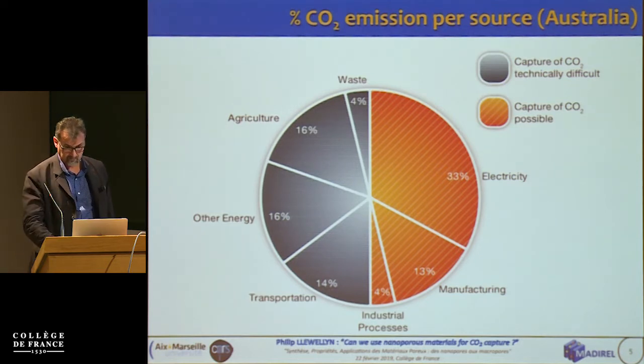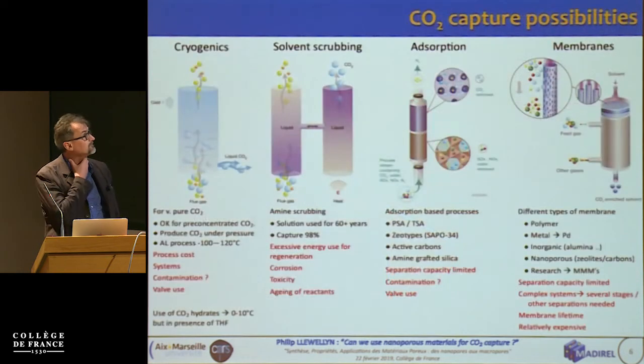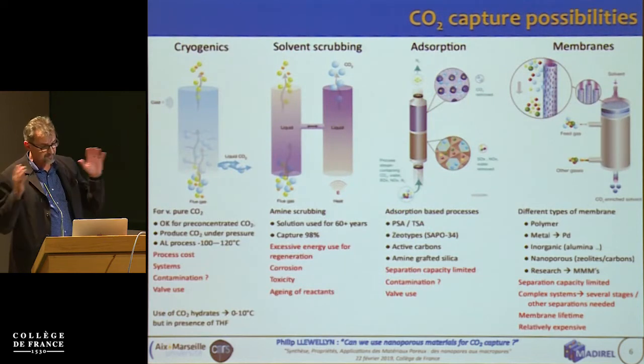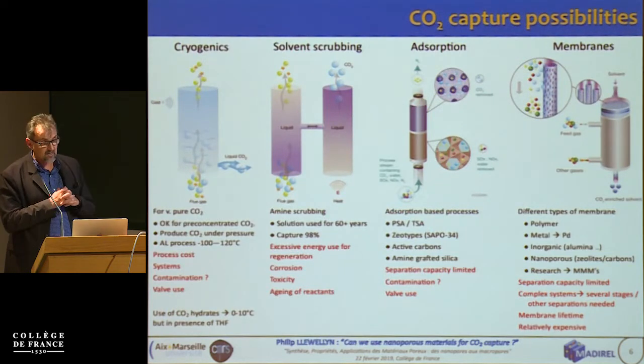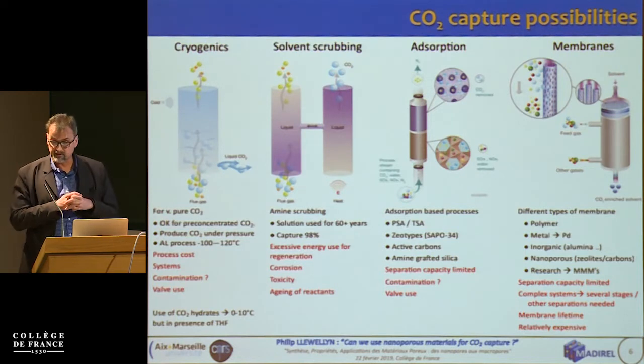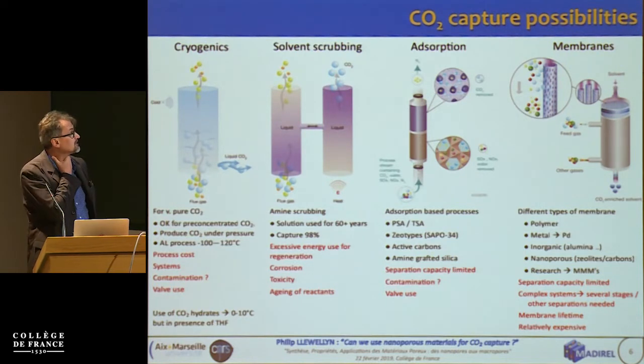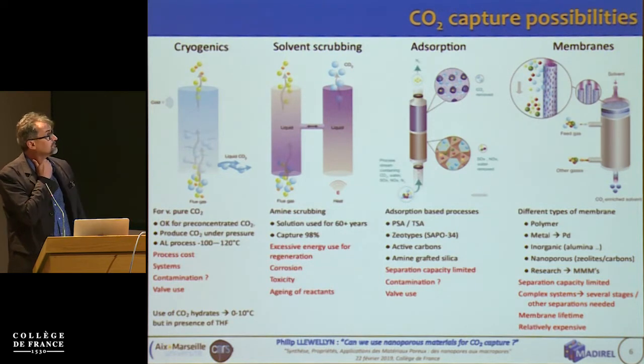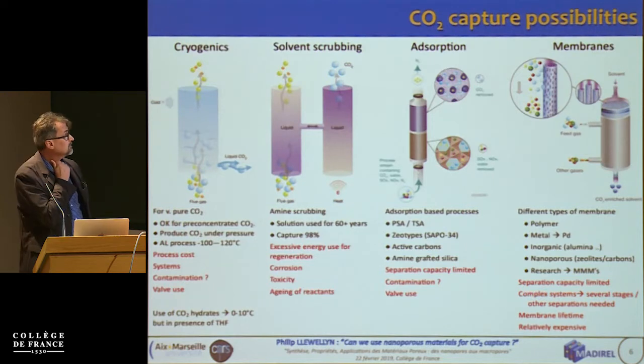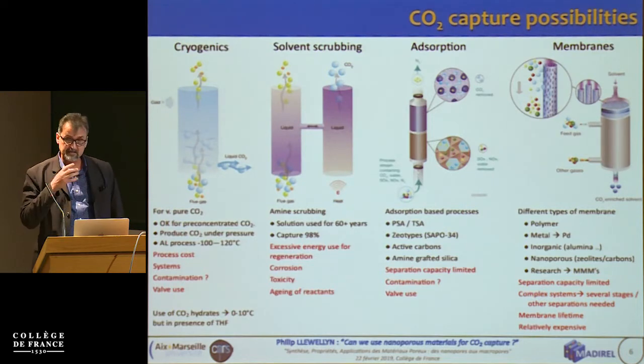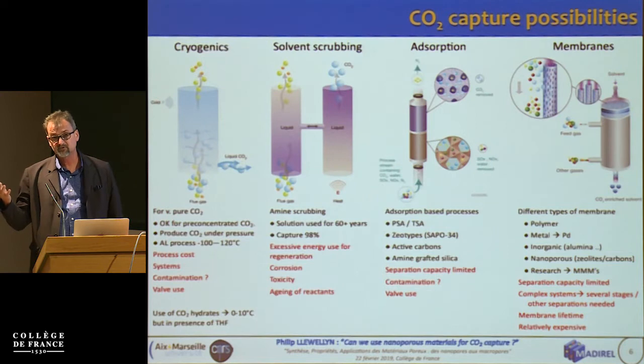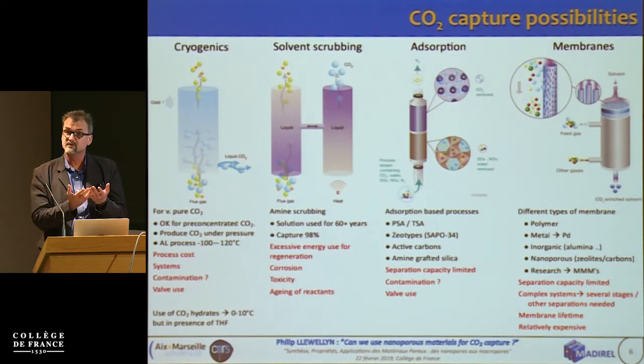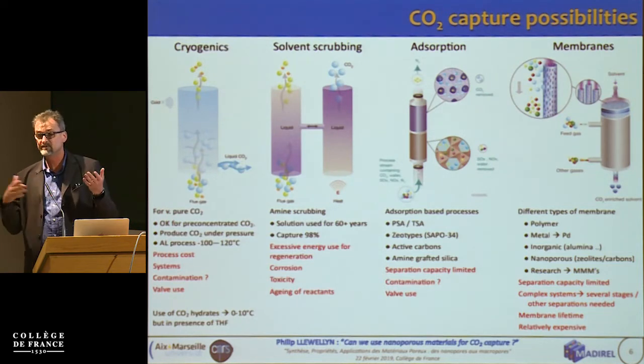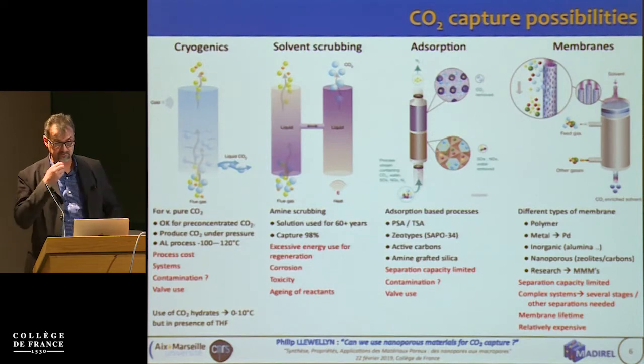Fine. So how do we capture CO2? Well, there are several different means of doing this, coming from left to right. So cryogenics, so the air leak process, which is, you can see in black all the things that are good for. So it's good for pre-concentrated CO2. Gives us really pure gas and quite under pressure. Having the gas under pressure at the end of the process is of interest because we want to then transport maybe the CO2. And this is done at about 110 bar, so quite high pressures.